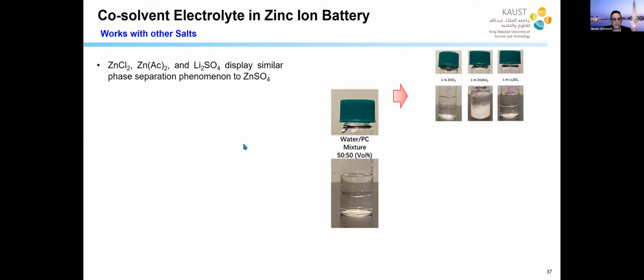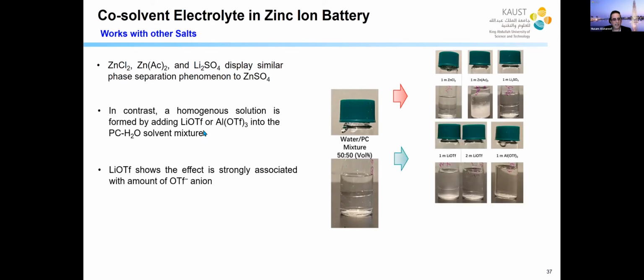When you put in these conventional salts, the solution remains immiscible; it doesn't mix. However, if you now add lithium triflate or aluminum triflate, which are different atoms, not zinc, you can still get a homogeneous solution. More importantly, for lithium triflate, if you double the concentration, you see the solution is even better.